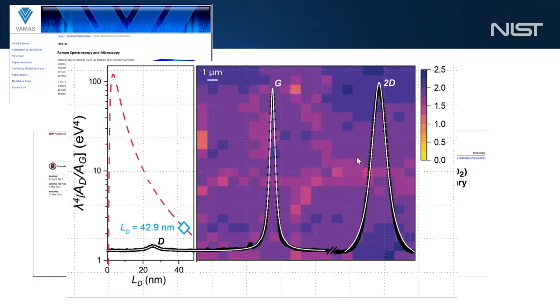I just want to put up here, because of this issue that we found in that particular graphene round robin, what we actually got was kind of a push from industry to characterize the graphene as grown. So most people in research anyway, we take the graphene from the CVD, chemical vapor deposition, that's how it's grown, onto a copper substrate. We rip it off there and put it on silicon dioxide, because that is how most of us make devices. Well, industry is saying, we don't want to look at a transferred graphene sheet. We want to look at our graphene as grown on copper.